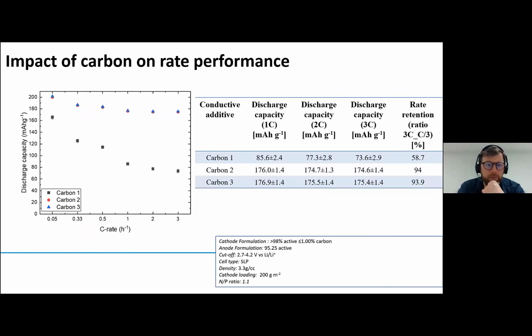What we have here is a quick demonstration. Unsurprisingly, we have to anonymize quite a bit of this. It's looking at carbon 1, which would be a baseline, just a carbon black additive, and carbons 2 and 3 are far more advanced, heading towards the carbon nanotube graphene school of thinking. And you can see a huge difference in terms of capacity as a function of C rate here.